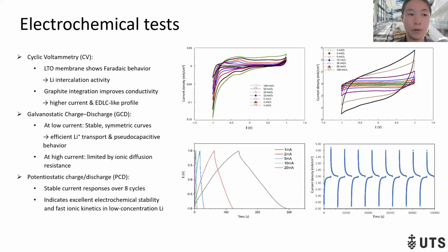And then we also did the electrochemical test. The CV test shows the LTO membrane has a Faradaic behavior, which shows the lithium intercalation activity. And after the incorporation of graphite sheets, the CV curves show the high current and electric double layer-like profile. And the GCD test shows that at low current, it gives stable symmetric curves, but at high currents, it's limited by the ion diffusion resistance. The PCD test shows a stable current response over 8 cycles, and it indicates excellent electrochemical stability and fast ionic kinetics in low concentration lithium.